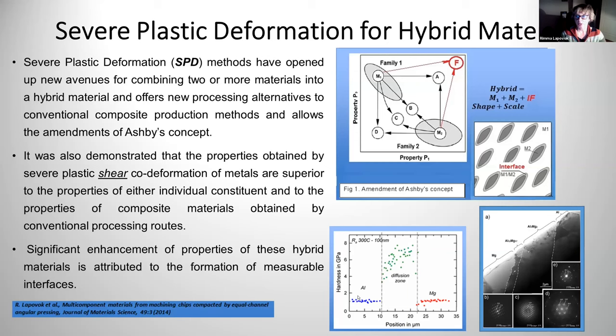In this picture you can see a hybrid material consisting of two constituents — aluminum and magnesium — with quite a large diffusion zone between them which has completely different properties from either material. In the TEM figure, you can understand why we have these different hardnesses, because we have different intermetallic phases within the measurable lattice interface zone.